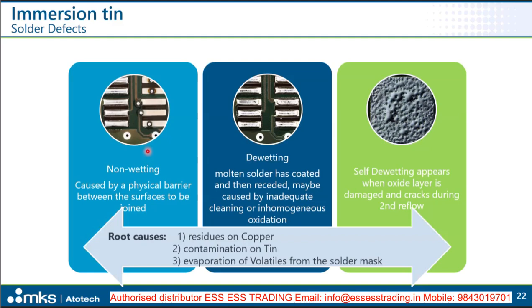What can be reasons for that? For the non-wetting, it's really caused by a kind of physical barrier between the surface and the solder, which prevents the solder from wetting. Dewetting is caused by the solder first wetting the surface, but then being removed. And we'll talk about the root causes for this later.